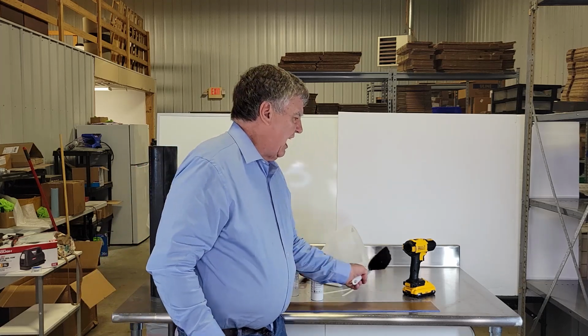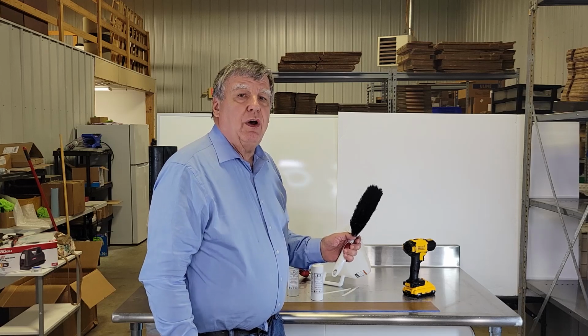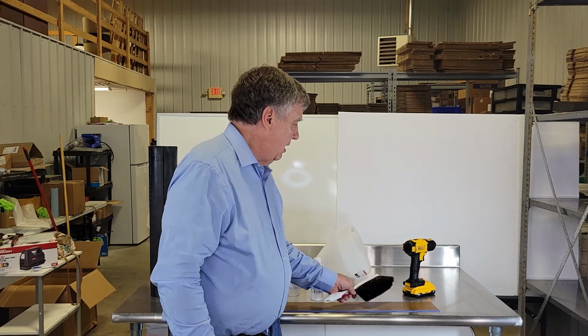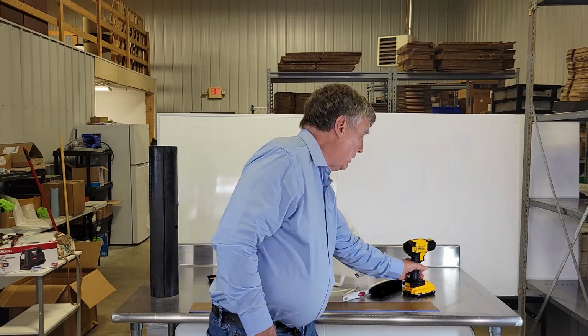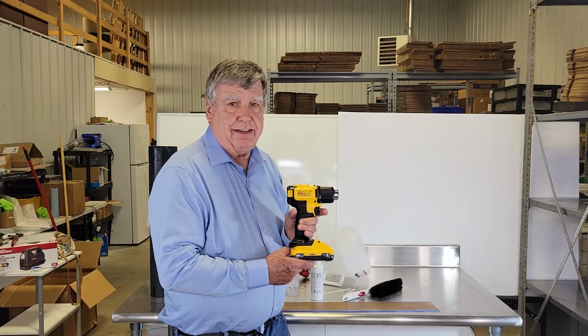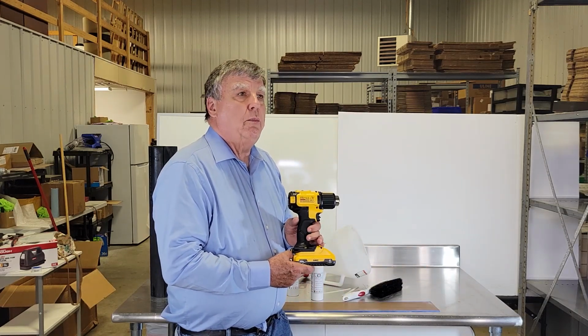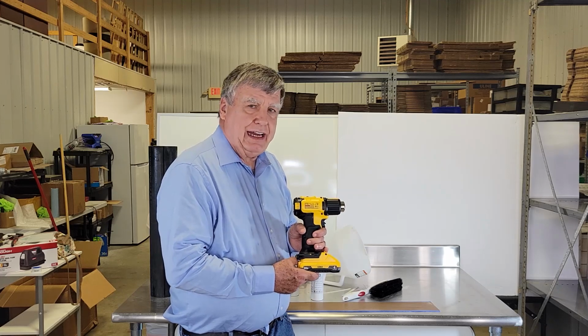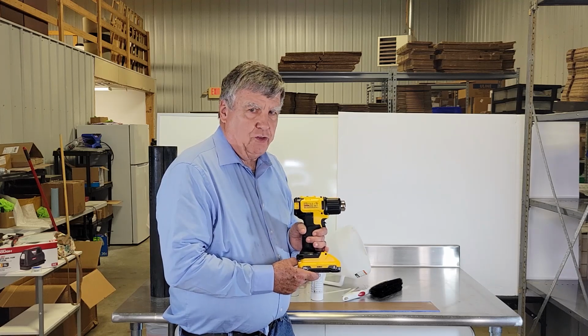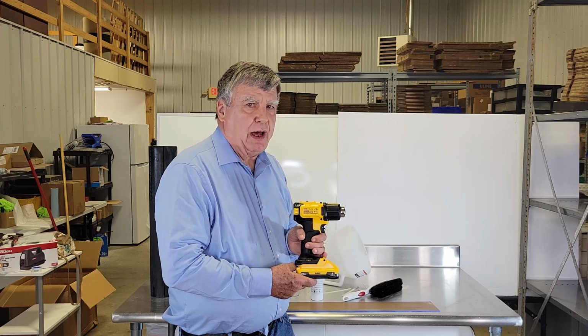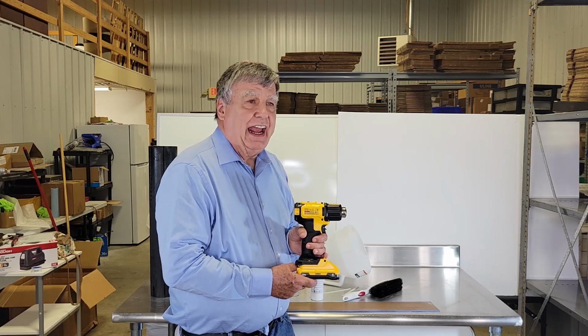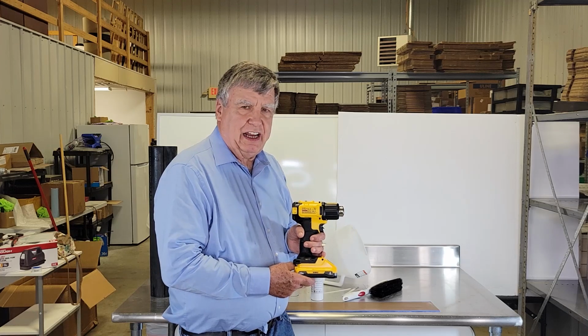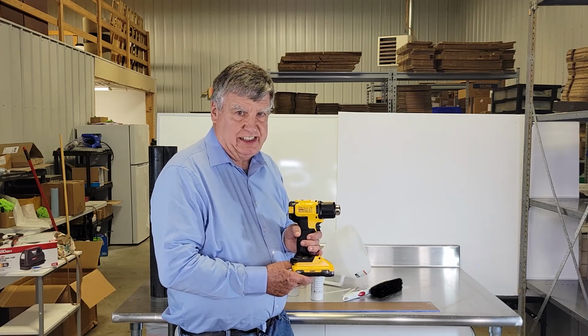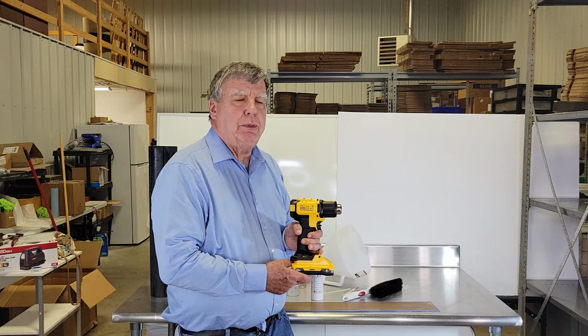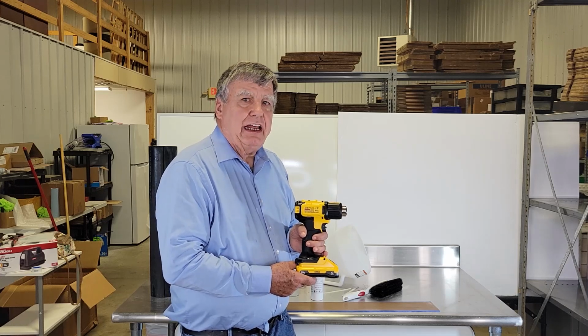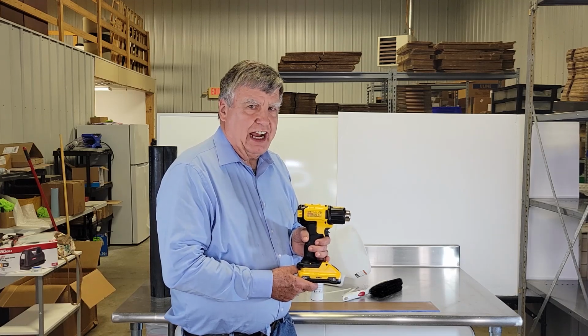Then there will be a brush. After each application of the filler, you want to brush out the excess. Last but not least, the final step of the process is to add heat. You bring the heat up after you apply the PTFE Tech Patch to about 49 degrees centigrade, and it will automatically increase between 56 and 60 degrees centigrade. And that heat will be maintained. That heat lets you know that the chemical reaction is working.